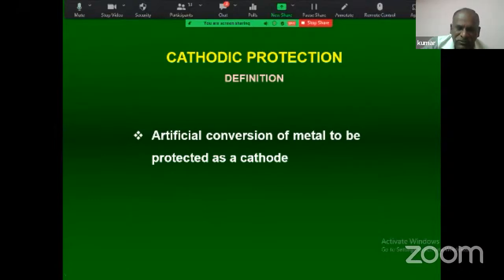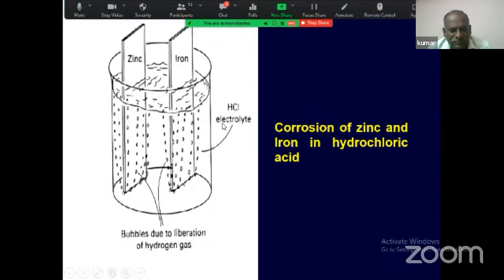So the more active material will corrode faster than the less active material. For example, you just see here, this is hydrochloric acid. If you suspend two materials, iron and zinc, in the hydrochloric acid, both will corrode, because in acid both corrode, but which one corrodes fastest? Zinc will corrode faster than the iron. Suppose these two are linked, zinc and iron connected, the iron will not corrode, zinc alone will corrode. That means, because of the connectivity, you are allowing zinc to corrode to protect iron. So iron will act as a cathode, zinc will act as an anode. So zinc corrodes fast and protects the iron. If you are not connecting, both are corroding.